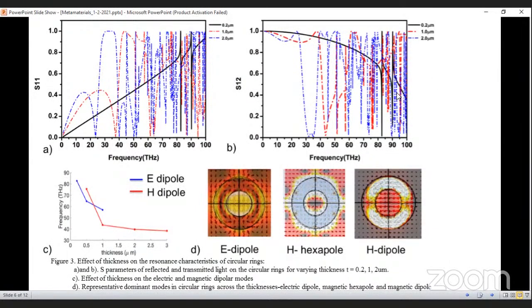Here we studied the effect of thickness on circular rings. As observed in the previous slide, very thin rings support only electric modes, and the magnetic modes are comparatively absent. But when we increase the thickness from 0.2 to 3 micrometer, then some magnetic modes are present.